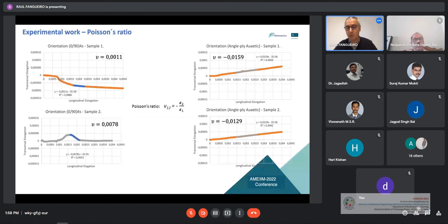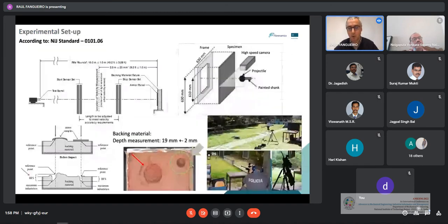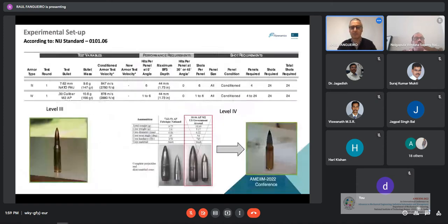But of course, as I said before, we want to develop materials, but we also want to test them, and we want to produce products based on this knowledge we are creating on composites and fiber-based materials. And as I said also, one of the interesting properties of these auxetic materials is this characteristic of impact and energy absorption. So we've been testing these materials for impact behavior using the setup you are seeing here, according to the standards, and we had the involvement of the police and the Portuguese army to do this, using different bullets, because they are also defined in the standards. I don't want to go into detail on this, but of course this is related to the energy absorption.